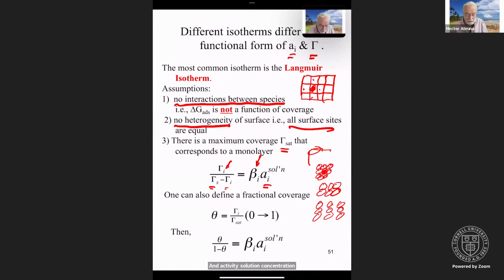It's often convenient to define a fractional coverage so that you can compare different species. If you have an absolute surface coverage, that makes life a little bit more complicated. And so you can talk about the fractional surface coverage theta. And so gamma I over gamma saturation goes from 0 to 1. When you have very little, then the fractional coverage is 0. When gamma equals gamma saturation, we basically go theta equals 1. If you do that, then expanding on the similar expression, theta over 1 minus theta equals the same term as you had before.